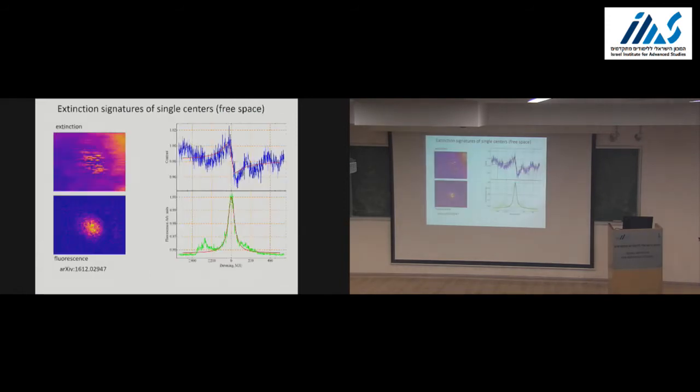Maybe one more point about the coupling of light and atoms. Usually you think that you need a high quality optical resonator, but if you have a very strong atom at hand, like one of those defects with a very strong zero phonon line, you can just focus your incoming beam and measure the scattered or absorbed photons. It turns out that for good optical emitters you can actually measure the shadow or reflection even from a single atom without any cavity.